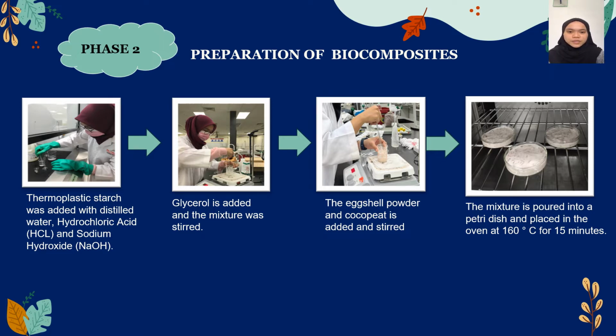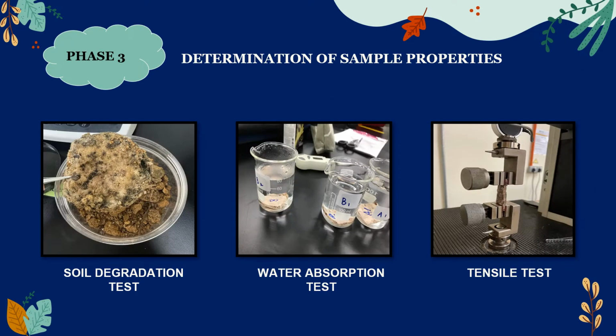Then put 5 grams of eggshell powder and 0.5 gram of cocopeat into the mixture and stir again on a hot plate until it becomes viscous. Then the mixture is poured onto the petri dish and placed in the oven at 160 Celsius for 15 minutes. After removing the sample from the oven, let the sample cool. Okay, phase 3 is the determination of sample properties. The sample properties were determined by 3 tests, which are soil degradation test, water absorption test, and tensile test.